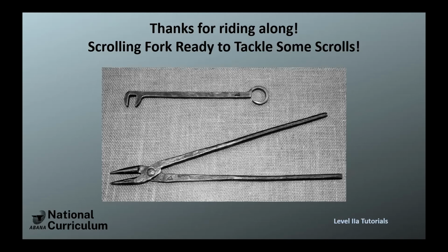No, this is just a thought, and I can't 100% prove it, but the way that you hold the piece in the vise is very similar to the way you do a half face blow. So you're going to get some material creep as you try and upset that second tine. And the front tine usually grows in length a little bit, which I think yours came out an 1/8 inch longer. That's probably where that material came from. It's because it's shifting down in the vise just a little bit. Yeah, pushing everything up. So you're actually forging on the anvil side, which is your vise jaw, like your hammer side. Yeah, that could be. You're just actually pushing that whole thing up.